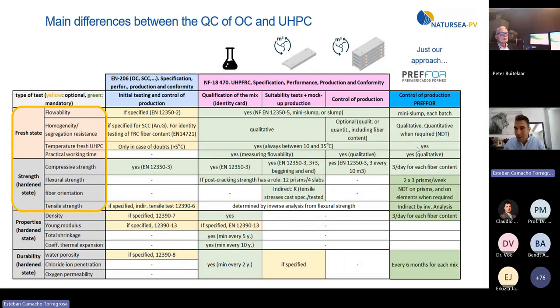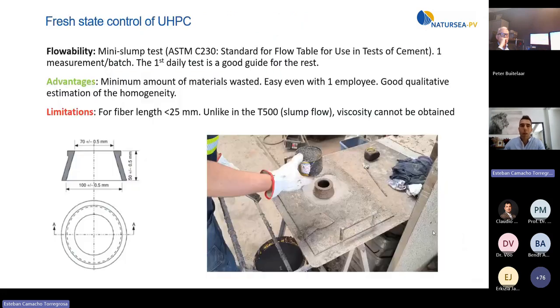Well, in the new column that you see on the left side, I am showing what we do in our factory. In our factory, obviously, we produce UHPC every day for different projects. And we have decided, and this is just our approach, because we found out that this is better for us in the medium and long term, that we also continuously control flexural strength, fiber orientation, and the density, because the density provides us interesting information, or can somehow predict what the compressive strength will be. And we also control durability. Every 6 months, we do durability tests to understand how our mix is doing.